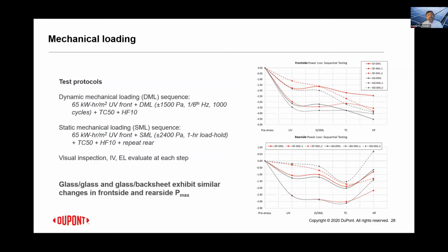But I'm showing here a couple of protocols that we have been taking these modules through, both on the front of dynamic mechanical loading sequence, where we don't do it just by itself. We actually combine it with a healthy UV dosage, followed by the dynamic mechanical cycle, followed by a thermal cycling and humidity freeze cycle. We do the somewhat similar one with the static mechanical load as well. The two graphs over here are showing the power loss, and I'm not sure if you can see this very clearly, the numbers are a little bit small, but in both these cases, what we are clearly seeing is that between the glass module and the glass backsheet module, there's not much difference in the power loss on the front and back once we take these through this cyclic accelerated sequential mechanical load sequences.